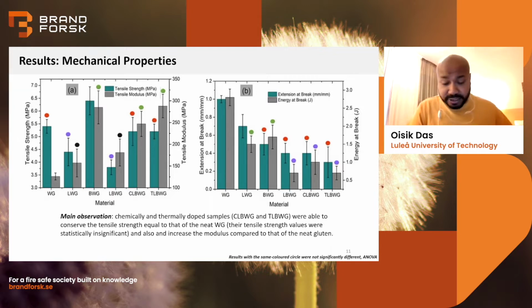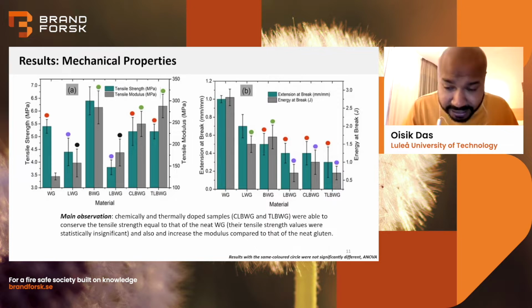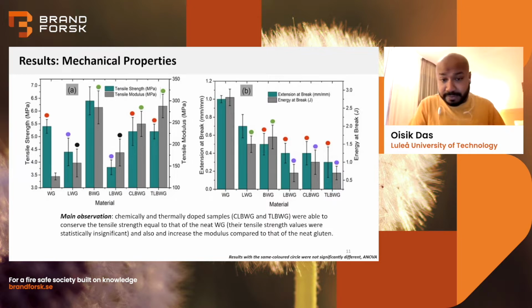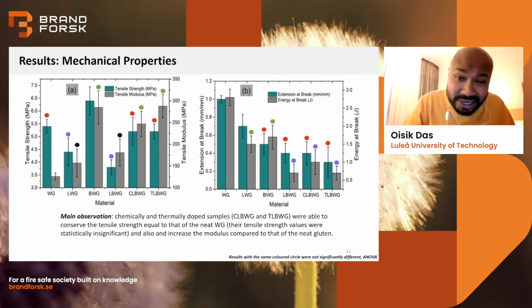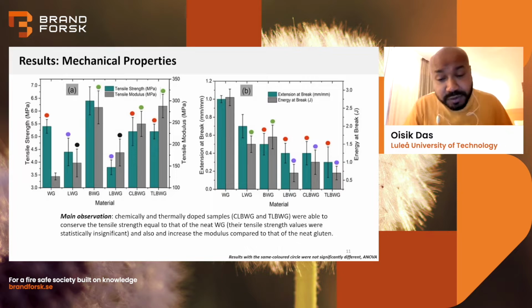The ductility has reduced, which is quite expected, because when we add any particles to any plastic, the molecular mobility of the polymer chain reduces, increasing the stiffness and reducing the ductility. But the main takeaway is that after doping with the chemical method and thermal method, we were able to conserve the tensile strength of the neat plastic, the control sample.